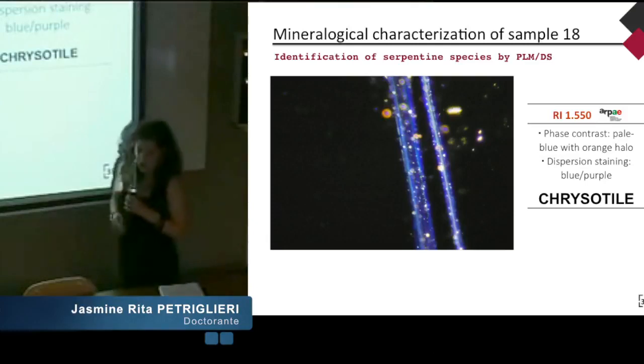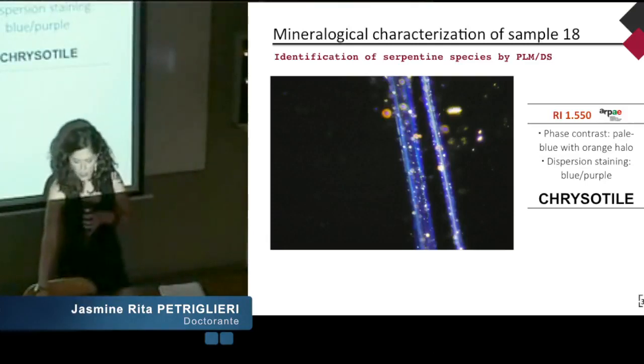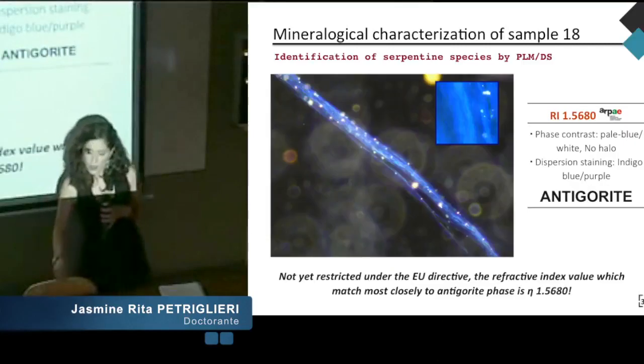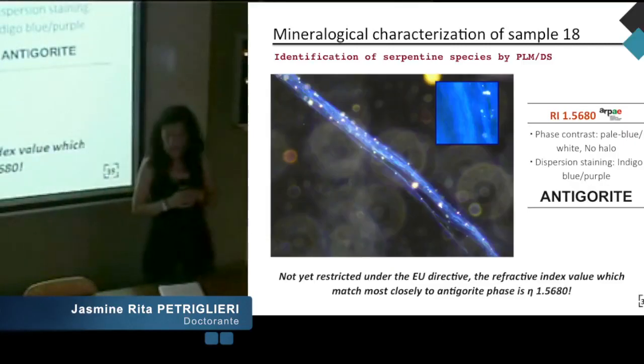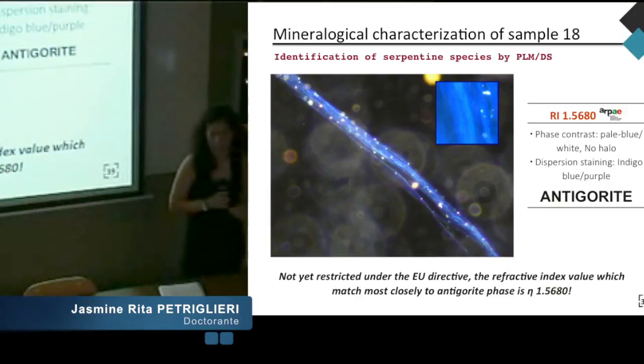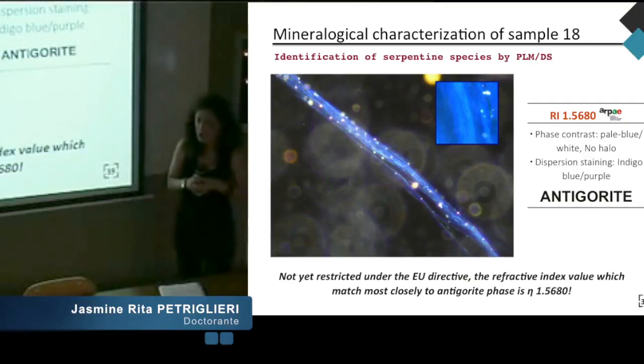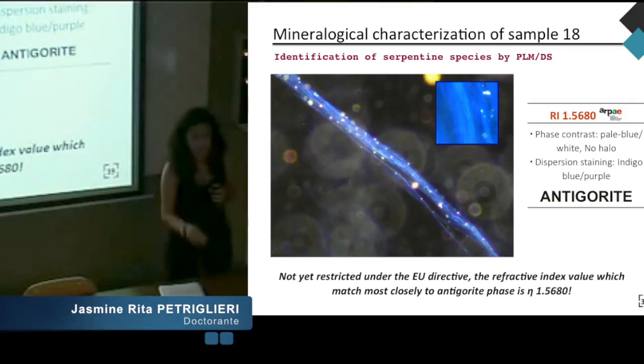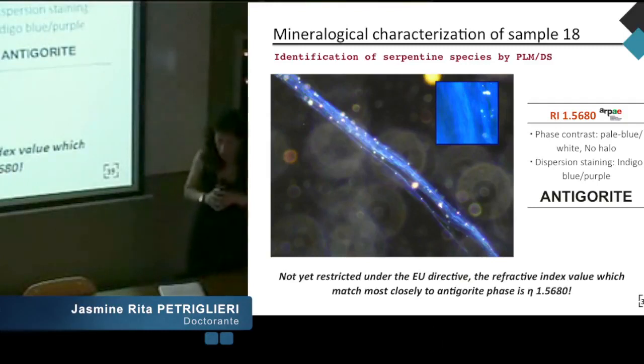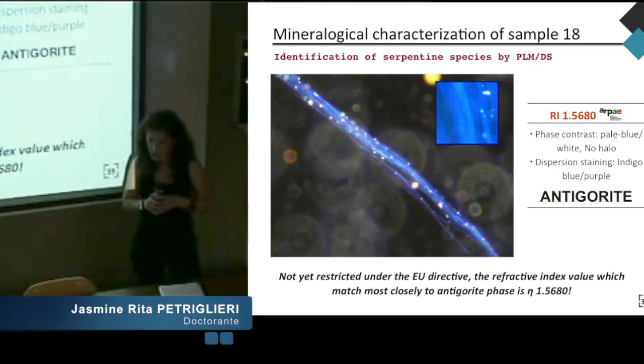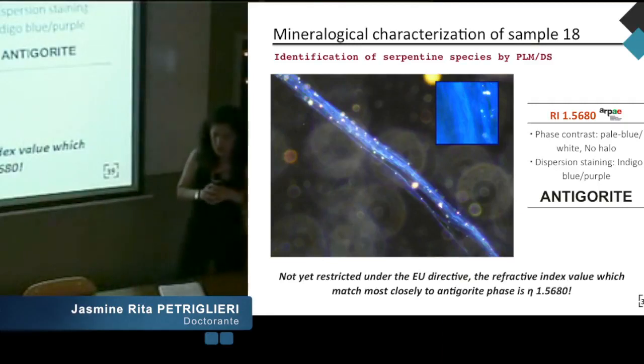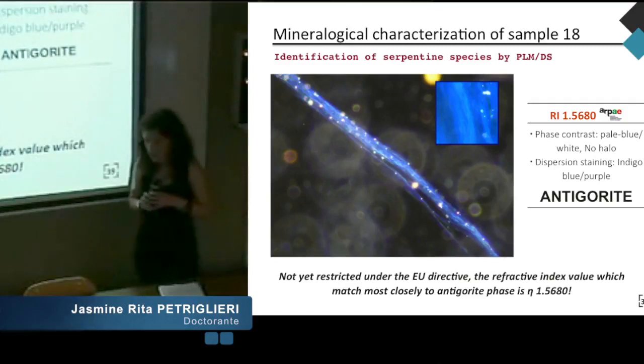For the chrysotile, we use the standard refractive index at 1.550. But for antigorite, there is not today a refractive index recommended by regulation, because, except for the New Caledonia context, it is not considered as an asbestos. A great survey of different refractive index liquids was carried out, and the refractive index value that most closely matches the antigorite phase is 1.5680.